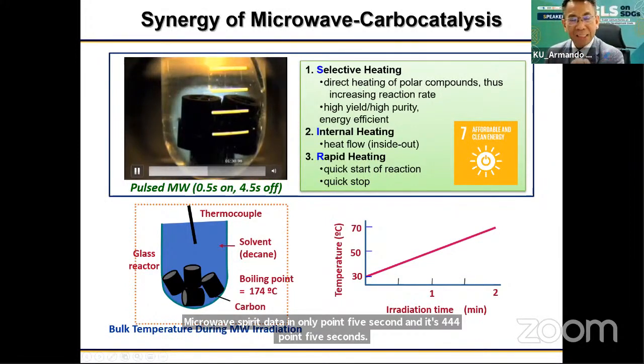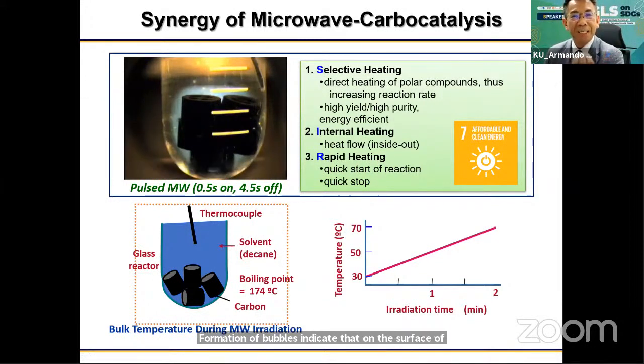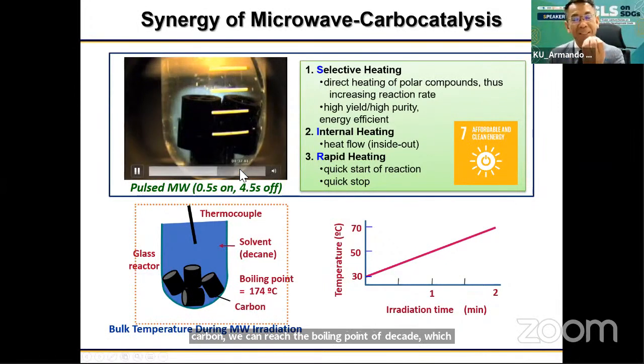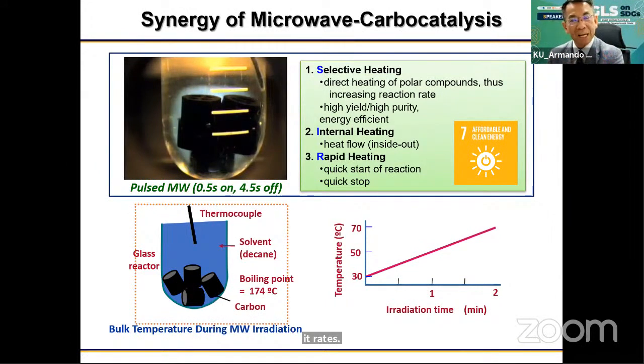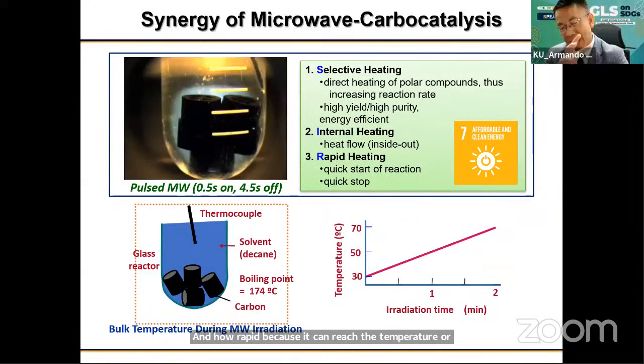Formation of bubbles indicates that at the surface of carbon, we can reach the boiling point of decane, which is 174 degrees centigrade. However, if you look at the temperature of the decane, it reaches only 70 degrees centigrade after about 2 minutes. This shows how selective, how internal, because it's only heating the carbon inside the solvent, and how rapid, because it can reach the boiling point of decane, 174 degrees centigrade, on the surface of the carbon instantaneously when you apply microwave irradiation. This is the beauty of the synergy of carbon and microwave heating.